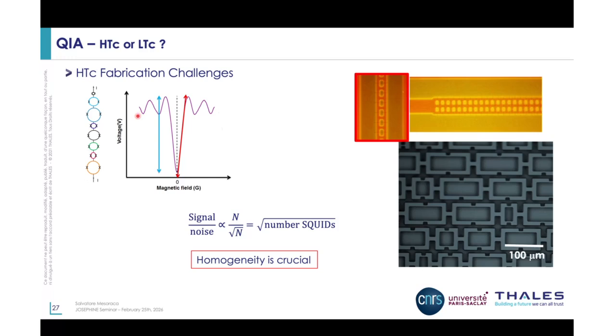Why is fabrication important? Well, something I've omitted to say, or I've said not that much, is that of course all of this SQUID importance and capacity of being a very highly sensitive magnetometer only applies if you're capable of making hundreds, if not thousands, of junctions and SQUIDs with the same characteristics. So the loop area will be different, and that's okay, but the junctions will have to be the same. So they'll have to be working at the same critical current, at the same critical temperature. Otherwise, they will be contributing to the noise, but not to the signal, and that will be detrimental, because by increasing the number of SQUIDs, we will increase the signal-to-noise ratio.